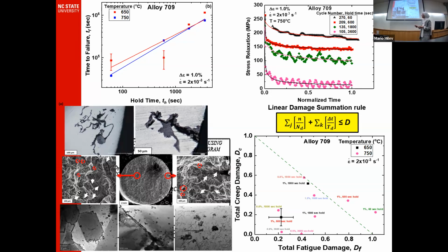We also look under the scanning electron microscope at the fracture surfaces of the sample after it fractures. We can see the intergranular pre-cavitation marked by red circles, and the white arrows refer to transgranular fatigue cracking. When we increase the hold time more and more, the damage mode is dominated by creep, so we observe more intergranular cracks than transgranular cracks.